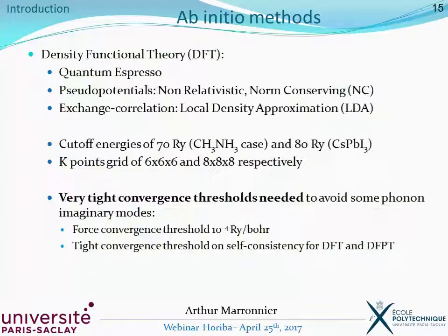So now on the methods I use for my ab initio calculation, this is your sleep moment if you do not use ab initio in your research. Otherwise, here are some details. To calculate the dielectric constant, I use density functional theory, and more precisely the Quantum ESPRESSO code, using very simple pseudopotentials and the LDA approximation. One important point here, as you see at the bottom, is that I needed very tight convergence thresholds to avoid some structural instabilities I found, especially in the cesium perovskites. I'll come back to this later.